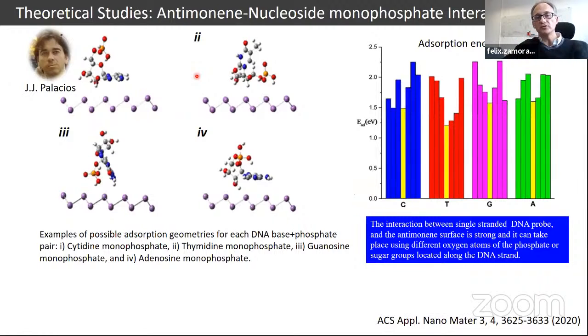In order to get more details about this interaction, in collaboration with Juanjo Palacios, he calculated the interaction between a nucleoside monophosphate, these molecules, and the antimony. These molecules are composed of the nucleobase, the phosphate groups, and the sugar groups. This graph summarizes all the results with the 4 nucleobases, and as you can see here, in all the cases we have a strong interaction. So the absorption energies are strong, values are high.